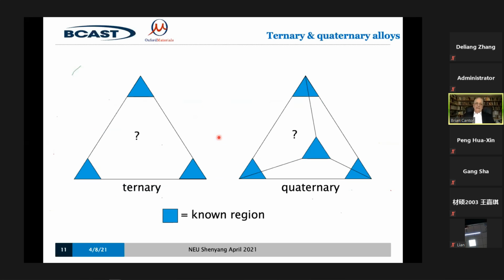There it is. So if we have a ternary system, we can imagine each point in this triangle is that we can imagine this is nickel, aluminium, and chromium at the corners, and each point in here is a nickel, aluminium, chromium, different composition. So our nickel superalloys are nickel mainly, with a bit of aluminium and a bit of chromium, and maybe a bit of something else. So they're in this region. If we have our window glass, it's silicon oxide here with a little bit of sodium oxide, maybe a little bit of aluminium oxide, and it's down in this corner here.